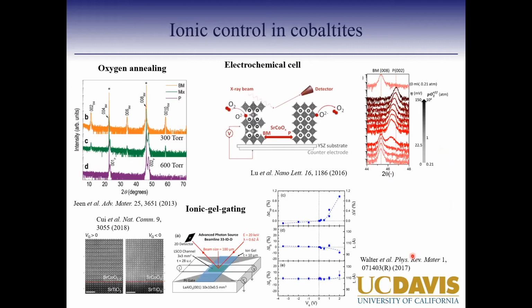These heterostructures have become very interesting, cobaltites especially, because you can move the oxygen ion in this material in and out as a function of different triggers. That's interesting for fuel cell applications, solid oxide cells, and also recently for neuromorphic computing. Traditionally, when you have a perovskite system, ABO3, people usually dope it with cations, A or B, and that gives a variety of interesting magnetic or electronic properties. But in the last decade or so, people have been really interested in changing the anion, moving the oxygen anion, because that has interesting applications for fuel cells.